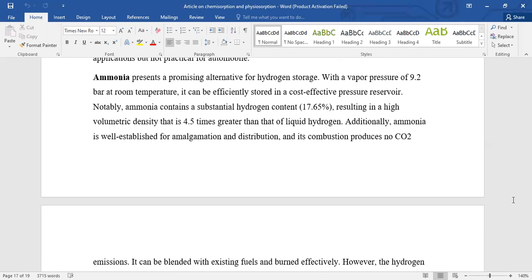With a vapor pressure of 9.2 bar at room temperature, it can be efficiently stored in cost-effective pressure vessels. Notably, ammonia contains substantial hydrogen content, 17.65%, resulting in a high volumetric density that is 4.5 times greater than that of liquid hydrogen. Additionally, ammonia is well established for production and distribution, and its combustion produces no carbon dioxide emission. It can be blended with existing fuels and burned effectively.